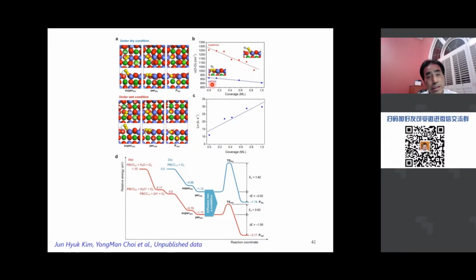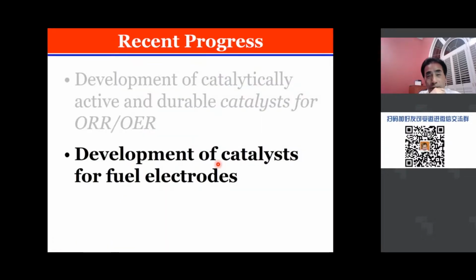And we built the model based on experimental results from the Raman measurement, which tell us what the species on the surface are, and did a DFT calculation, and this ultimately explains why the PBCC gives you higher catalytic activity in the presence of water. It is mostly because the surface adsorption of water creates an OH group on the surface, and that actually accelerates the adsorption of oxygen and makes the adsorption, dissociation, and reduction of oxygen occur on the surface more readily. Yeah.